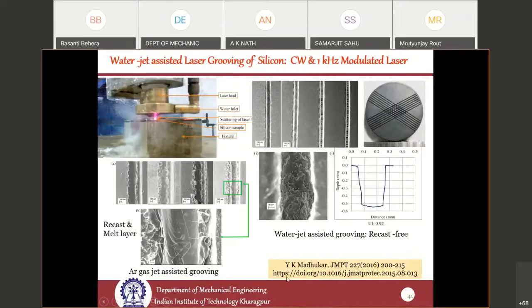Here at IIT Kharagpur, we also did experiments with a CW laser and a laser operating at 1 kilohertz modulated power. We could see that, with respect to argon, where we get a lot of recast and melting, when using high pressure water jet assisted grooving, you get very good quality grooving done on silicon wafer. You can get very straight walls, clean without any melt or recast material left on the surface.